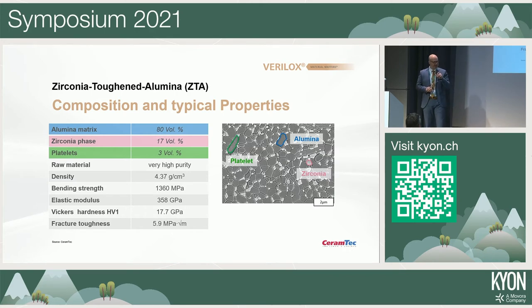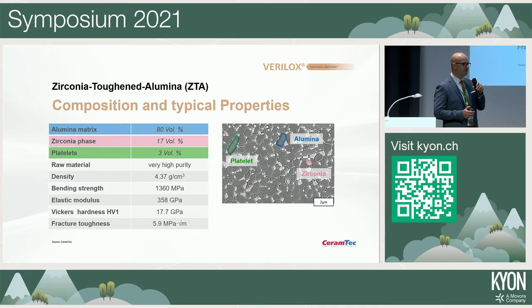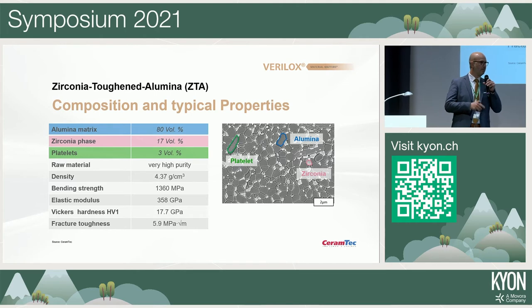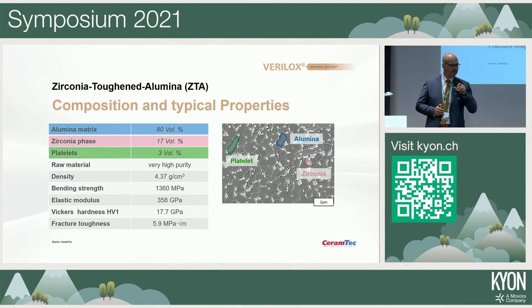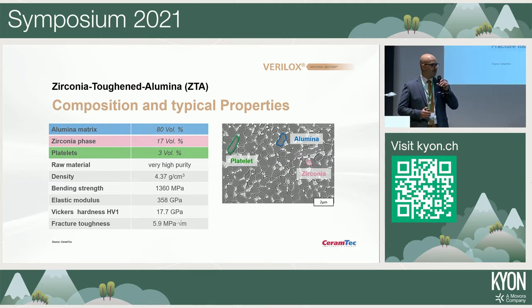The second thing, and that's a very important factor, is the hardness of the material, with 17 gigapascal. The hardness of ceramics is close to that of diamond, which means in a hard state, the only way to machine that material are diamond tools or, the second possibility, other ceramics which are harder than the one that you want to manufacture. The disadvantage of that is the material is expensive. So we have to keep that in mind.